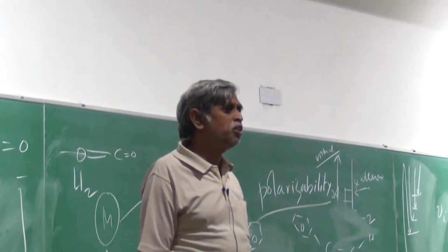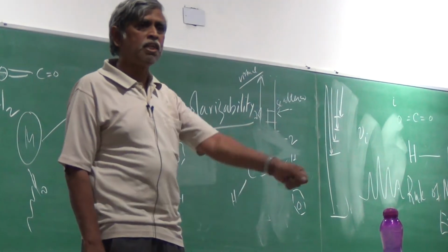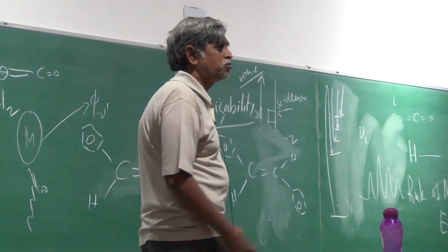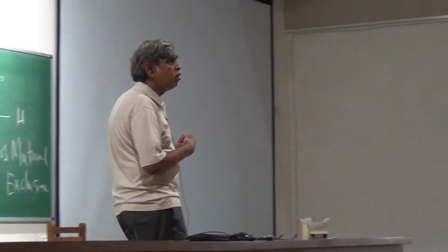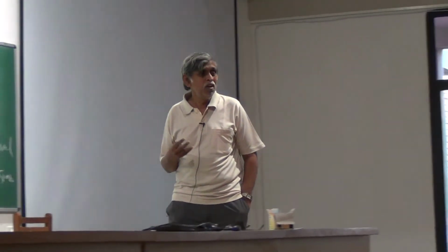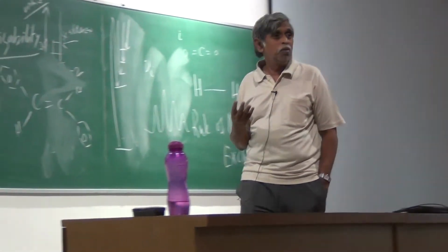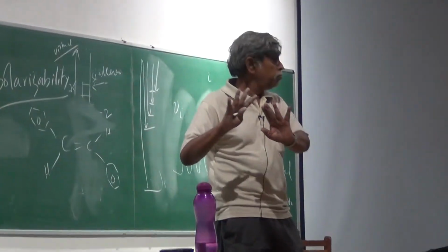And of course, whatever you have lost out in terms of the scattering efficiency, you can always make up for it by just jacking up the laser intensity, which of course you can do. And therefore, it's a very smart thing really to be looking at wavelengths that are quite long in a Raman experiment. If you ask them what wavelengths they are using, they'll always give you 632. 632 is the wavelength for the helium neon laser, or maybe a 700 plus, which is a diode laser, and so on. People use that.